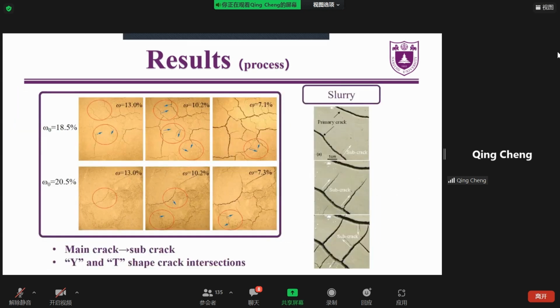And the crack propagation manner of the soil samples compacted on the wet side, with a dispersed structure, is more similar to that of the slurry samples investigated by previous researchers. We can find that the primary cracks initiate first and the subcracks initiate at the existing primary cracks and almost perpendicular to the primary cracks. This can be explained by adopting the maximum stress release criterion.